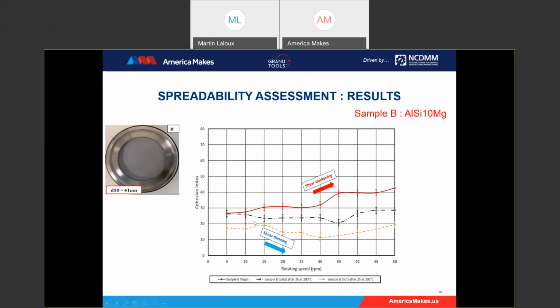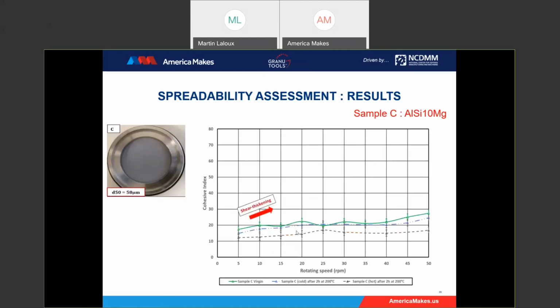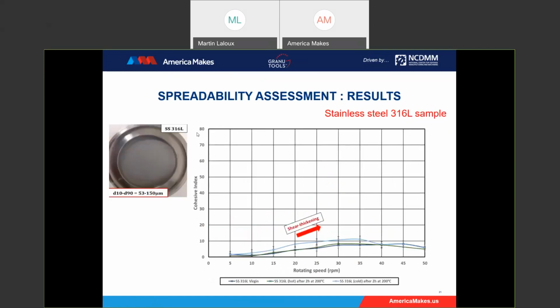And then the cold powder, we observe a linear behavior. So for sample C, we observe a shear thickening behavior, but this is quite the same. So the rotating speed has no really big influence on the spreadability and on the cohesive index. And finally, for the stainless steel, the results are quite close. So we observe here also a shear thickening behavior, but the curves are really close to one another.